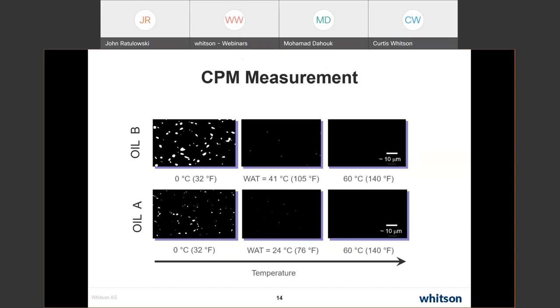Even a well done measurement is going to give you something that's a little bit lower than the actual thermodynamic phase boundary. I didn't have any DSC traces, and I'm not really that good at interpreting them. So I'll just show you a CPM measurement, and you can get a feel for why it's difficult to see the actual onset.